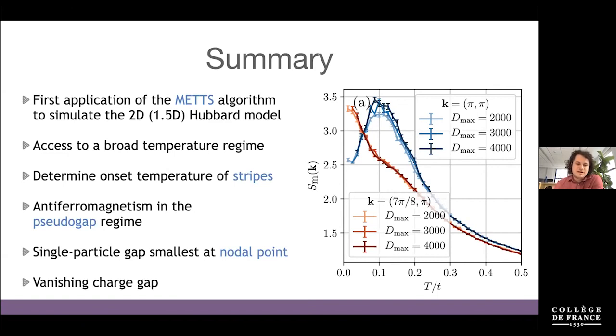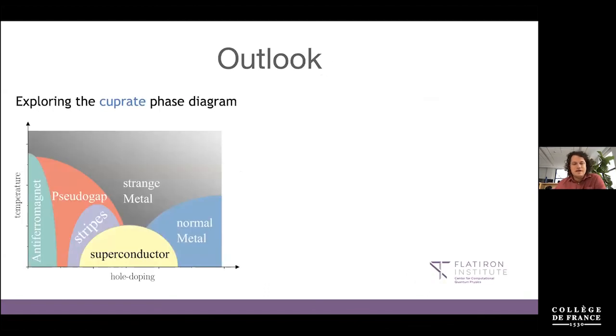We established the onset temperature of the stripes and find this antiferromagnetism in the pseudo-gap regime. We find also that this single particle gap is actually smallest close to the nodal point. And we observe this vanishing charge gap. And yeah, with this, I would like to give you a little bit of an outlook, what we would like to do in the future.